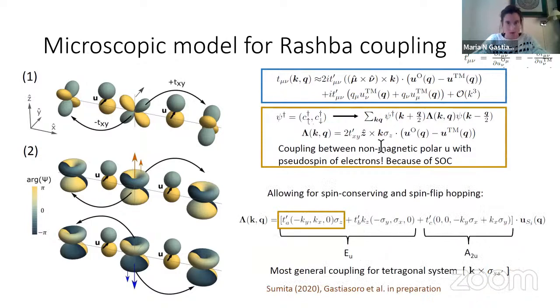And what I showed here is a particular interorbital process. In our case, which had tetragonal symmetry, this is the most general coupling. If you have a cubic system, or an isotropic cubic system, you should have this K cross sigma. If you lower your symmetry to tetragonal, the EU is going to be split into an EU two-dimensional representation and a one-dimensional representation A2U. This process is basically giving you one of the EU components, but in a very similar way, taking into account the other T2G orbitals where these new hopping channels will be induced, you can get all the others.